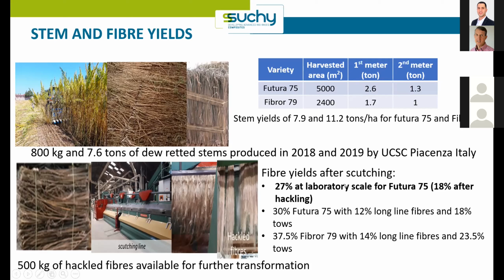It was very difficult to transfer those settings to the industry, but still some pretty encouraging results were obtained, with 12% of long fibers obtained after scutching, and 18% of tows for the Futura 75 variety, and a little bit more fibers in the Fibror 79 variety with 14% of long fibers and 23% of tows.